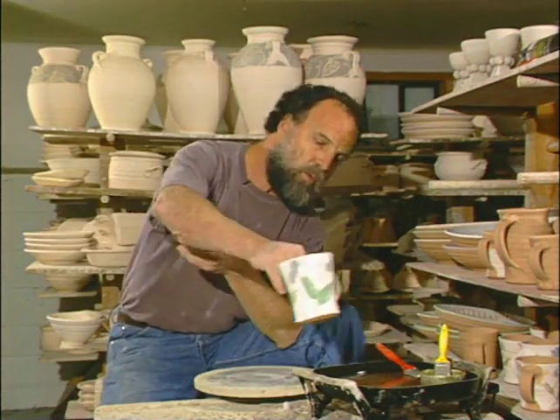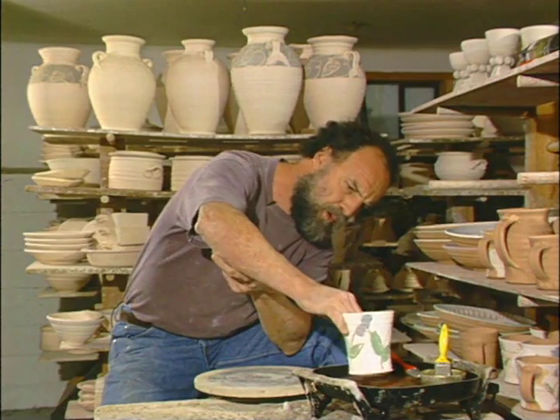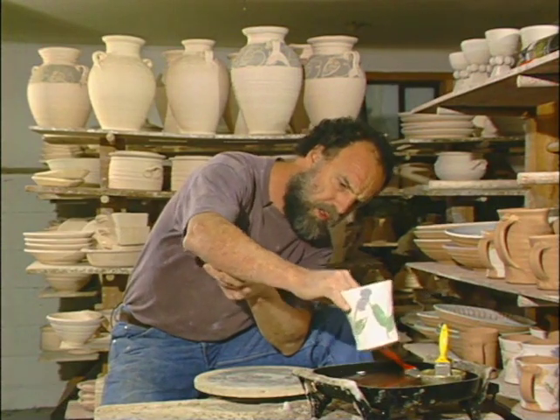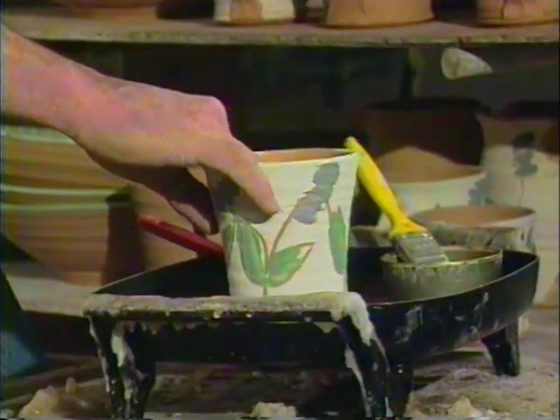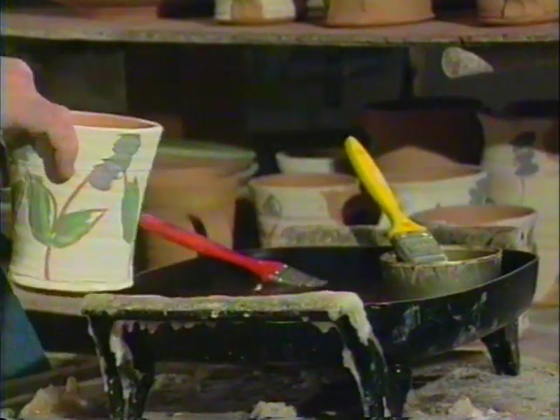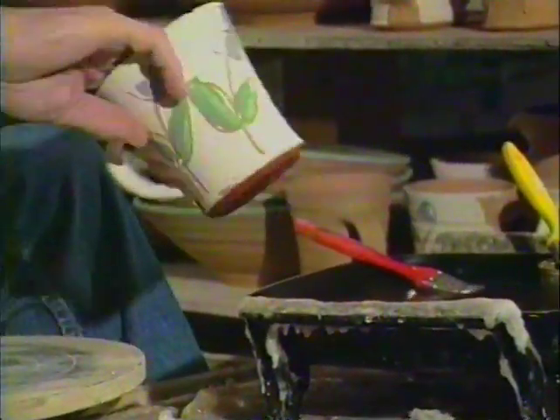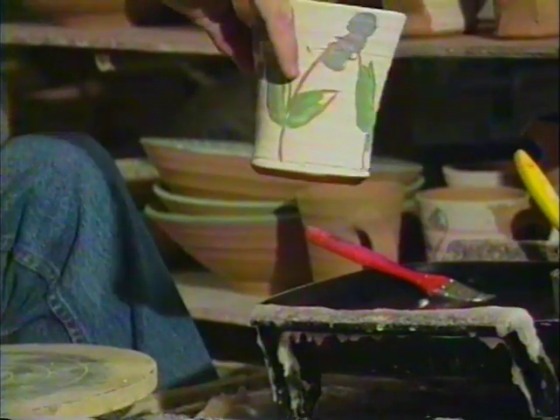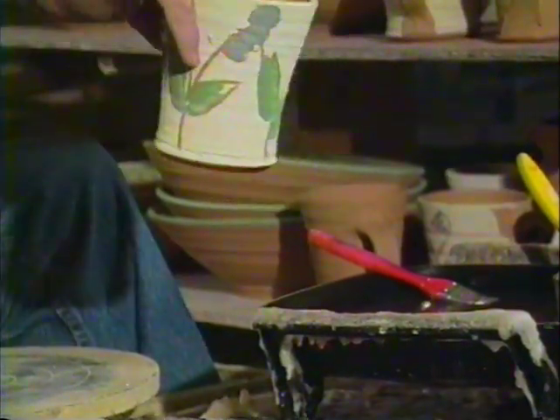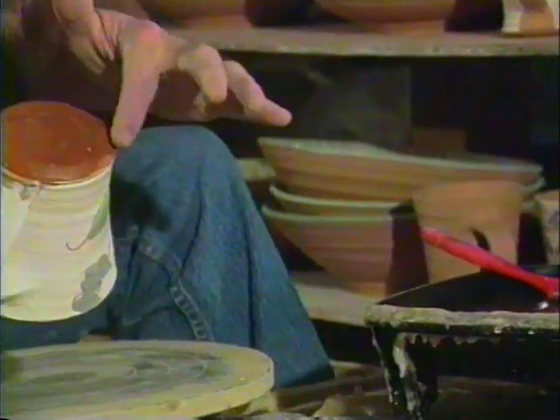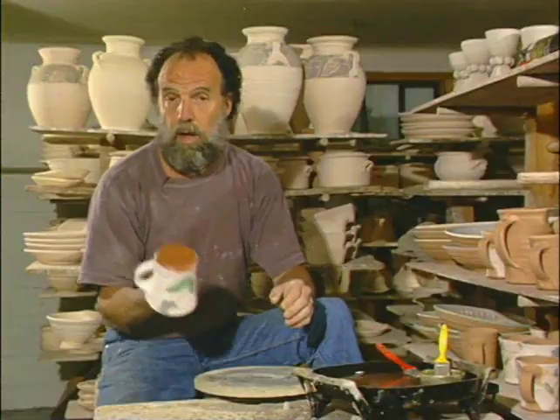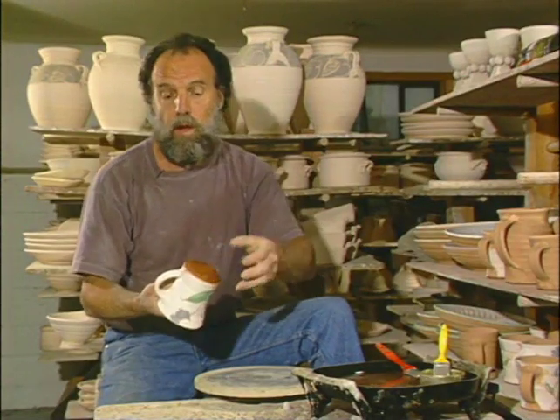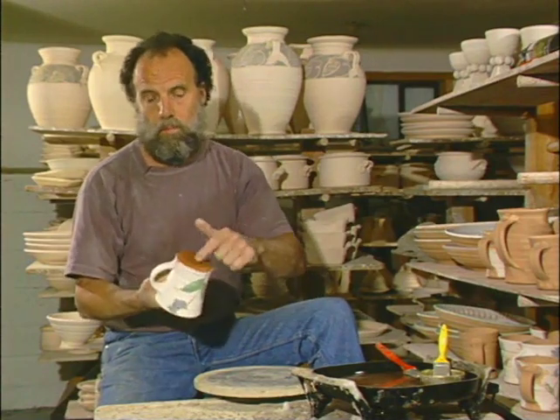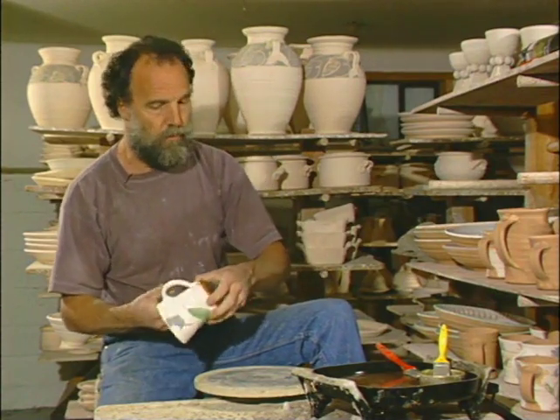Okay, so you can either apply the paraffin. Note how I'm supporting myself so I won't dip it in inadvertently, by dipping, like so, scraping off as you take it, making sure that it's dry before you turn it upside down, otherwise there'll be a little dribble of wax down the side of the pot. You can see I've covered the bottom with wax. So now when I dip this into the glaze, or pour glaze onto it, none of the water-based glaze will stick to the bottom of this pot.